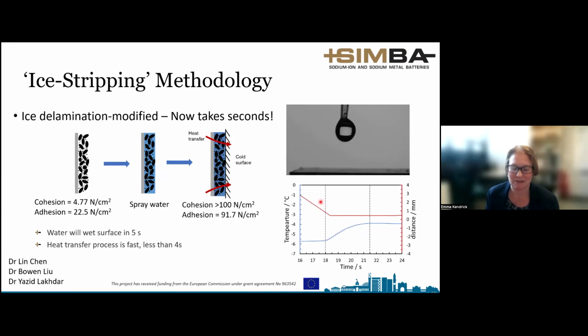What happens is the water goes into the electrode structure, the porous electrode structure. It freezes because the heat transfer is so quick in those thin electrodes. We can take the heat out, the electrode sticks to the surface very quickly, and then the adhesion to the surface of the cold plate is so much greater than that to the adhesion of the current collector that we can simply just peel it off. We can wet the surface in about 5 seconds, depending upon what the electrode is, and then it freezes in about 4 seconds, as you can see from some of these measurements that we've done.